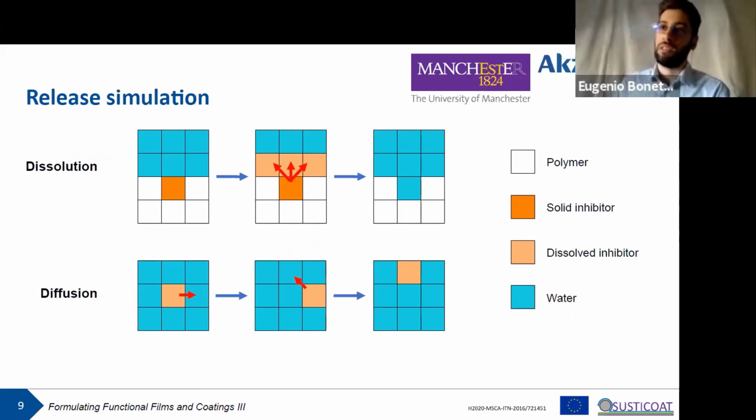Then as I said, the rules simulate the phenomena of dissolution and diffusion. The dissolution rule is applied to the solid, soluble cells, which generate dissolved cells until they are completely dissolved and they disappear. While the diffusion of the dissolved cells is simply represented as a random walk through the water-filled cells.